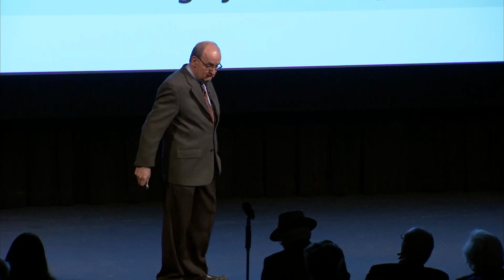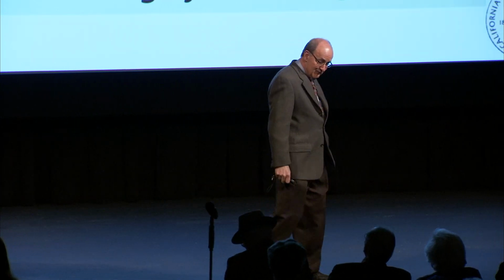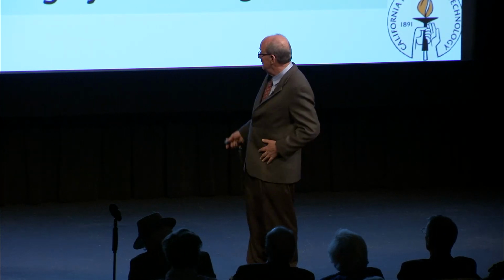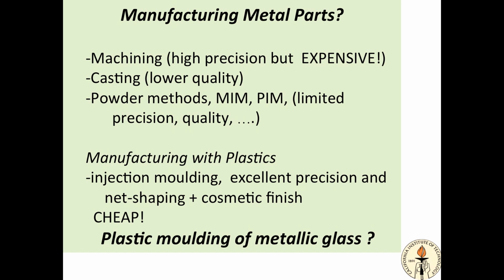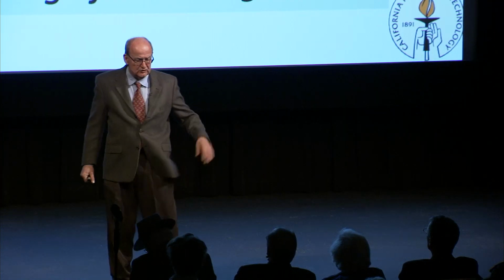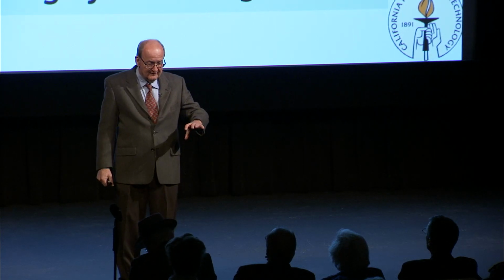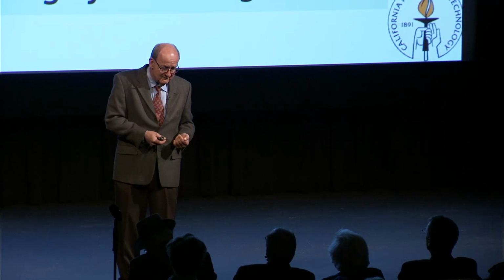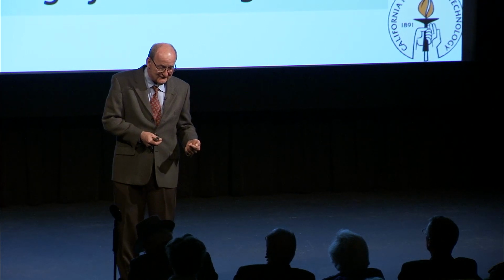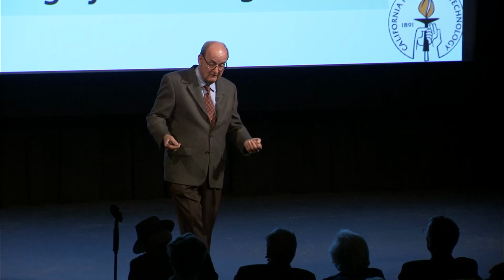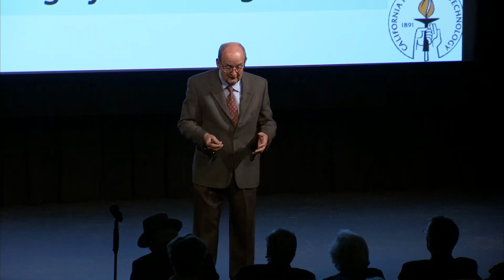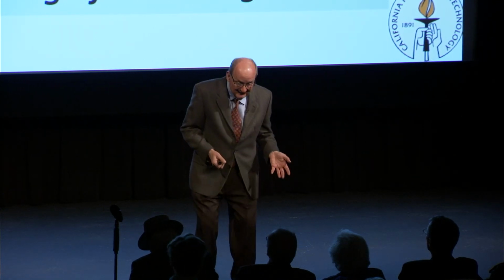You can cast it. Casting's okay. It's got all kinds of issues, but castings, you make engine blocks out of it. If you want to make a precision part with thousandths of an inch, you don't cast it. In the modern world, a lot of the stuff you use every day is made by metal powder injection molding. What do you do there? Well, you take metal powder, you mix it with plastic powder. Plastic powder is a glass with a low glass transition temperature. You heat it up, it softens, and then it carries the metal along, and the mixture can be molded.